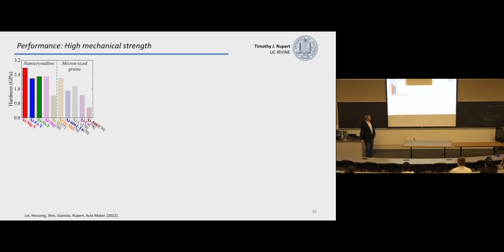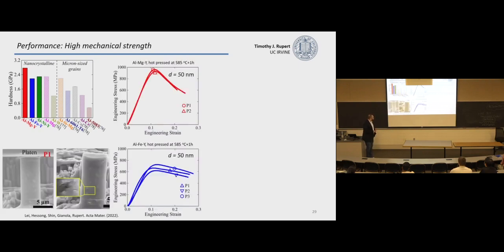But getting to the punchline, you end up getting some of the strongest aluminum you can find. So here is some preliminary data on hardness. So we're harder than many of the other nanocrystalline comparisons. But we can also do mechanical testing. Here we're starting with micropillar compression. So the aluminum magnesium yttrium alloy has a strength approaching 1 gigapascal, which for aluminum is pretty crazy.